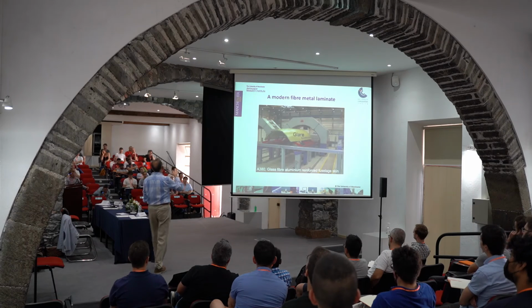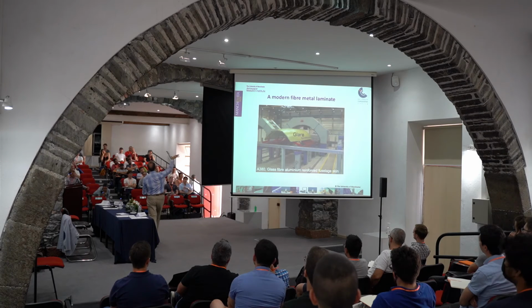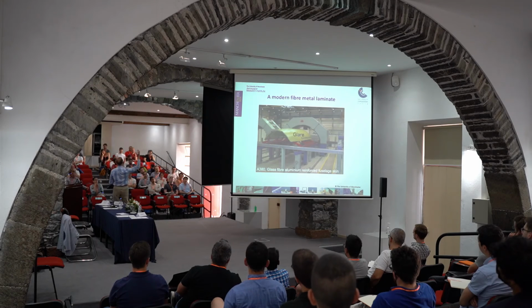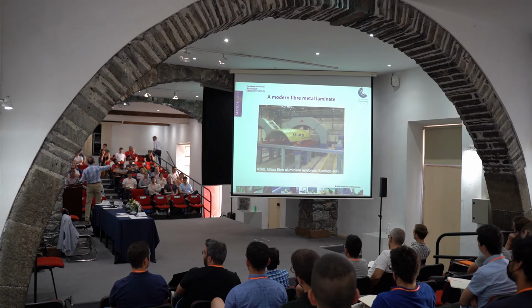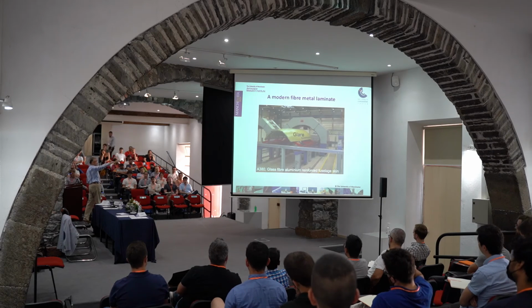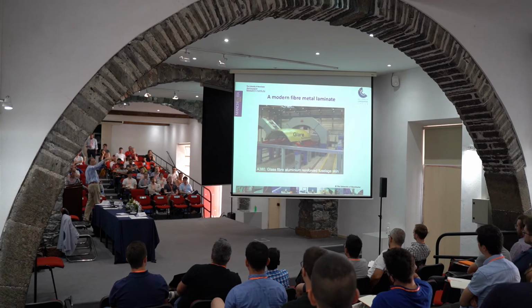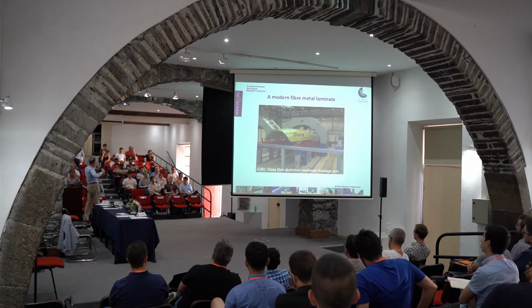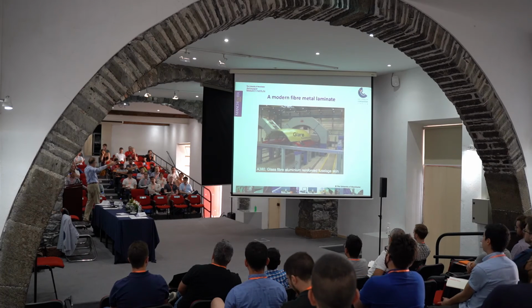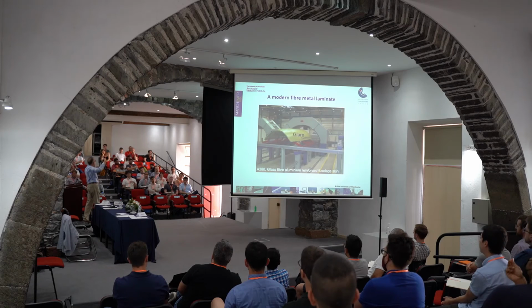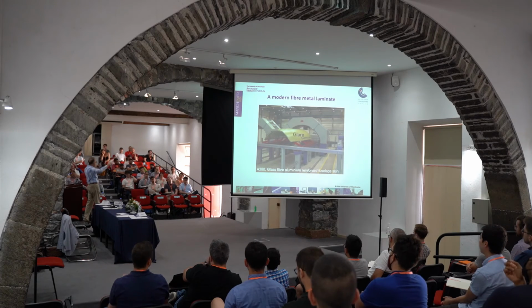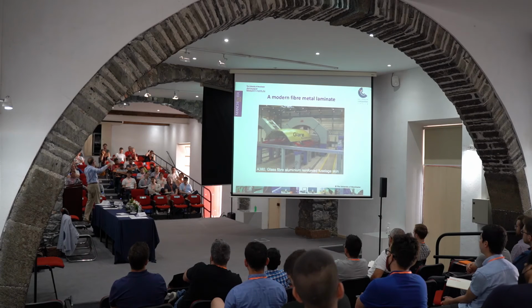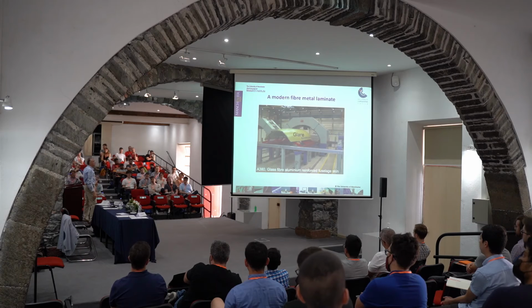And of course, Airbus introduced, in order to make tougher systems that can sustain this kind of thrust, explosion, absorb this type of energy without getting perforation, a GLARE system, which is a glass fiber aluminum reinforced laminate. So you get the ductile behavior of your aluminum, of your metal, and you get all the benefits of your composite, which is the lightweight structure, which dissipates energy in the form of matrix splitting, delamination, fiber breakage, but without getting perforation.